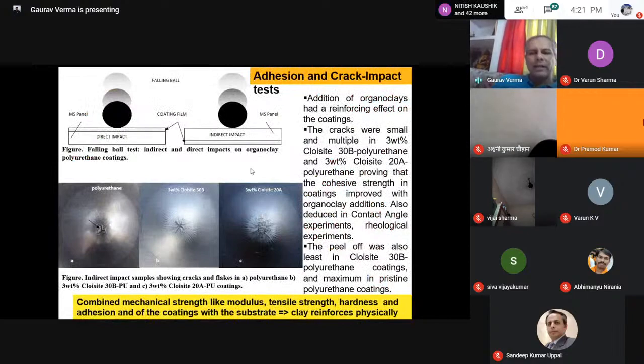At many times, your automobile undergoes some kind of impact due to an unfortunate accident or a malfunctioning engine. And that is where the coatings come off, and these images are actual real images of coatings which we have put on metallic substrates. And what we are trying to show here is that if these coatings can be made better or better adhere to the substrates, the functionality of protecting the substrate becomes much better for a nanocomposite coating as compared to a clear coating or a pristine coating.